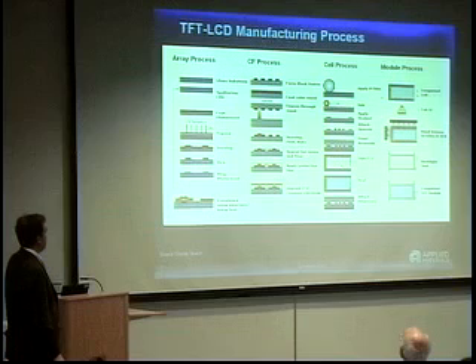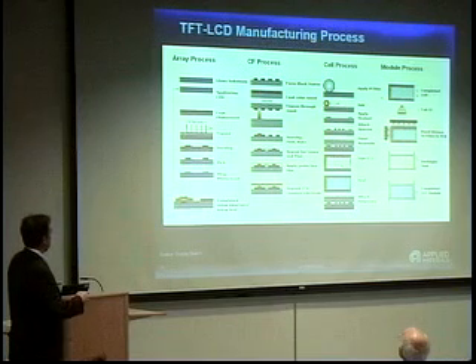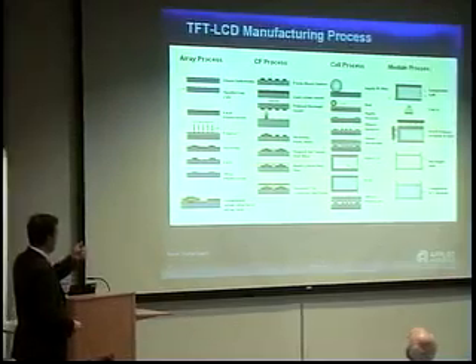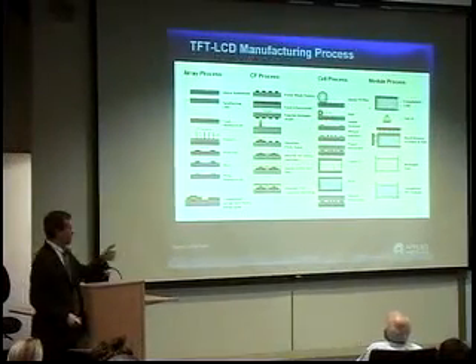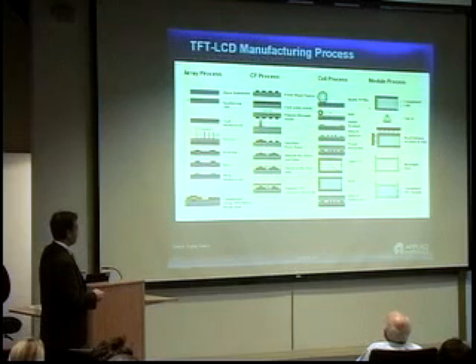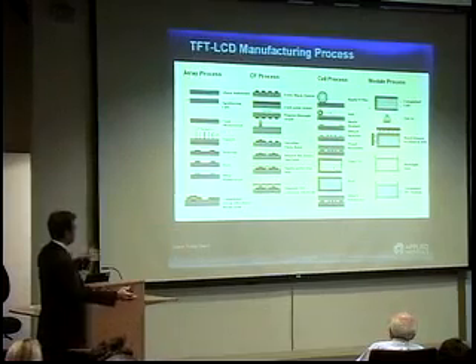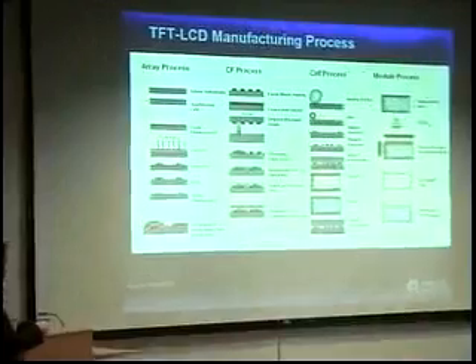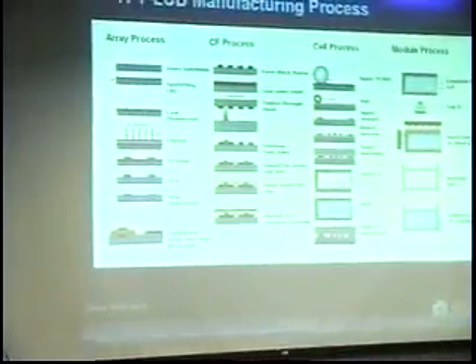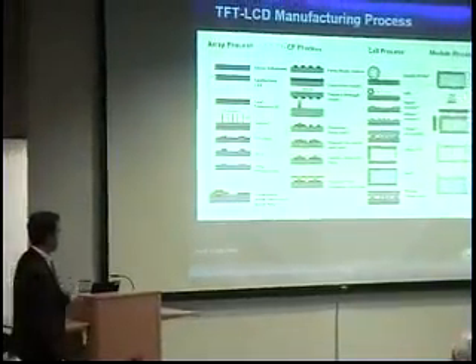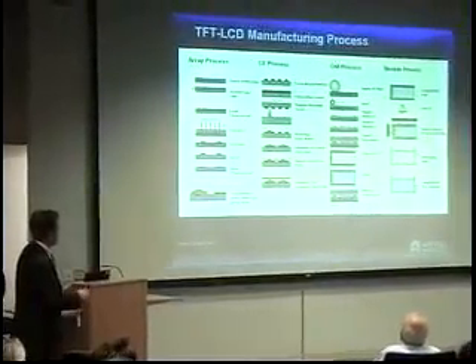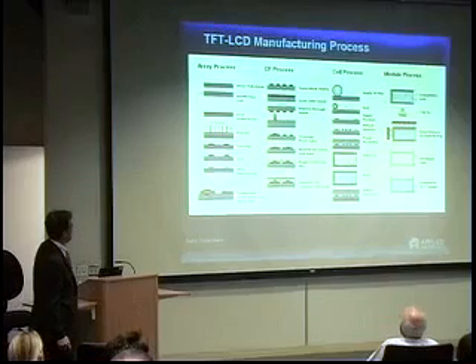This is the typical LCD TV manufacturing process. You make this structure, which is a transistor to turn on and off the red, green, blue pixels in every location. You make a color filter, which has the red, green, blue color that this turns on and off through the liquid crystal. And then you have the thing that basically assembles the whole thing. So there are many steps with thin film layers, with patterning, with lithography, and patterning of color filters, and an ITO, or transparent conducting oxide, to turn this on and off without the interconnect being visible. So a lot of semiconductor-like processes.